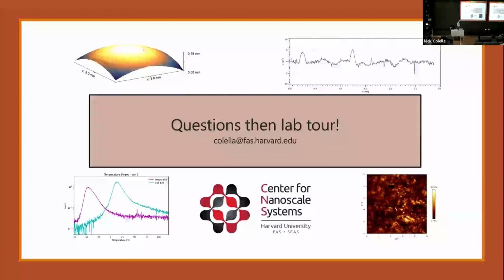Great question. So we need to have the surface exposed because we need the probe to push down. Additionally, we need a pretty thin sample. So the height needs to be less than a centimeter, often less than 7 millimeters. So sectioned tissue is generally good, and that's what people generally do. So if you want to like embed in paraffin and then section, that's ideal. We just need some exposed surface that we can push into. And we're typically pushing in about 100 to 200 nanometers, just for reference.